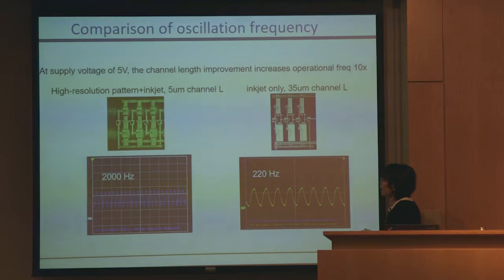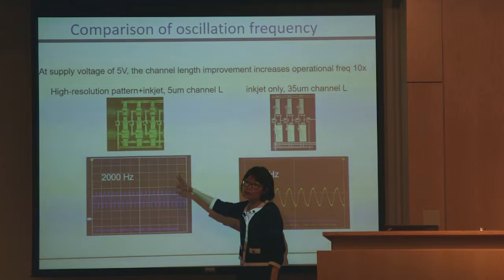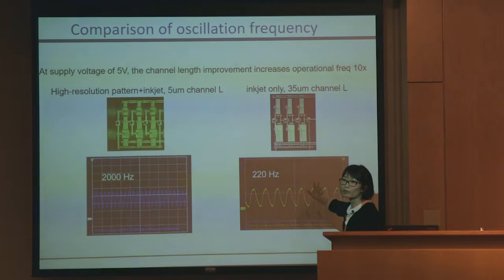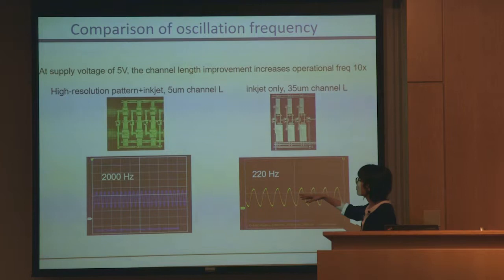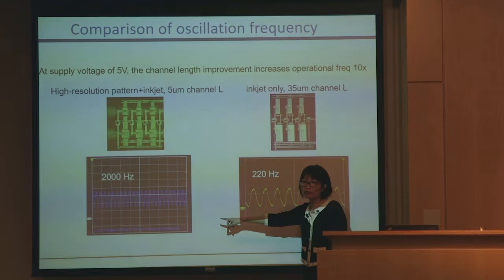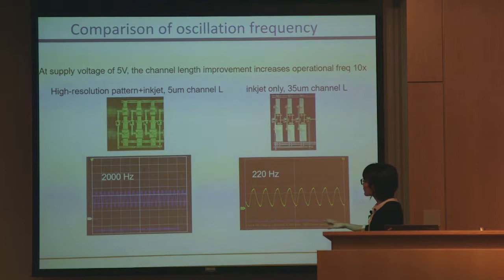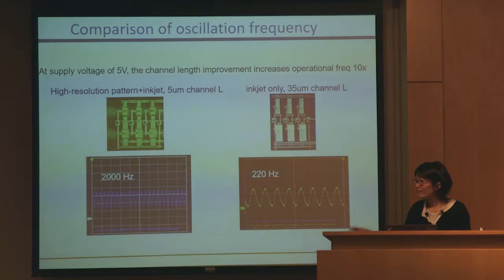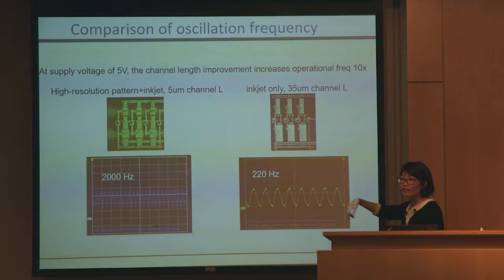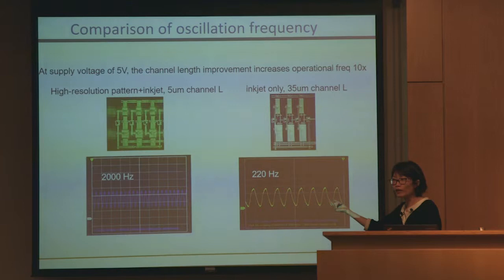So with the hybrid approach, we shrunk the channel by five micron, and then inkjet, the narrowest channel we could approach is 35. So with this simple change of the resolution, we increased the frequency of our oscillator by 10 times. Yeah. So if you were paying attention to my Moore's law, actually, this is decreasing the channel width by 7 times, and it should be inversely proportional, right? So I should have 7 to the square. So I should have 50 times improvement, but I only have 10 times improvement here.